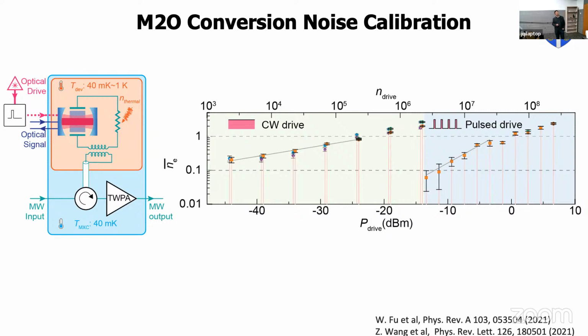So the trick we apply is to use a pulse drive. The pulse is on the order of 2 microseconds, so that will not compromise the operation of your qubits, but reduces thermal noise quite significantly. You can see that as you switch to the pulse mode, your noise drops by another 20 dB. Then you can further increase your pump intensity, and at 0 dBm power, you start to have 1 noise photon. So those are very efficient techniques to reduce the added noise of those converters. And we are improving this further. Hopefully, in our next generation device, our thermal noise is going to stay at the 0.1 level at the base temperature of the dilution refrigerator. That's something we're working on.